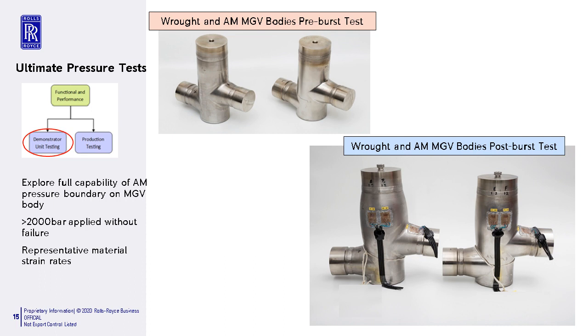So in order to explore the full pressure capability of the AM components, we carried out what we expected to be an ultimate pressure test, really in order to initiate failure, and this was on both an AM valve body and a wrought valve body, really to enable a level of comparison between the two manufacturing methods. So we designed a pressure test rig to go well beyond the design pressure of the components and apply an increasing internal pressure at stages to the blank top bodies.